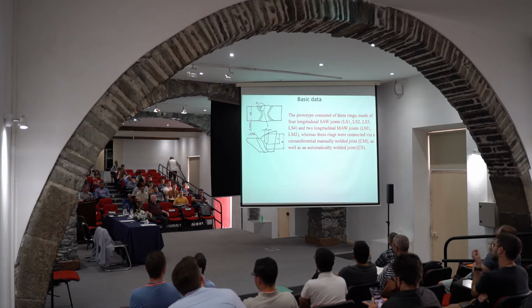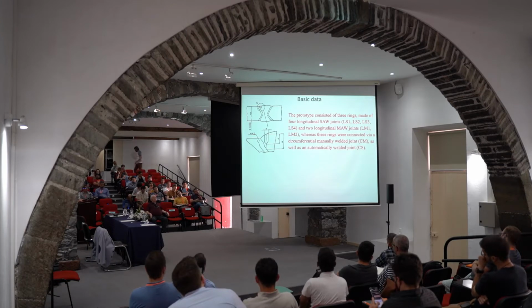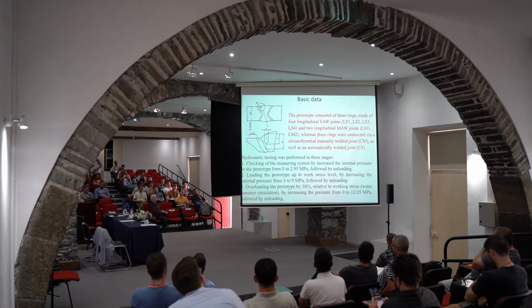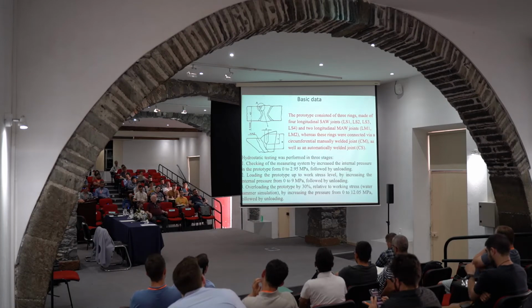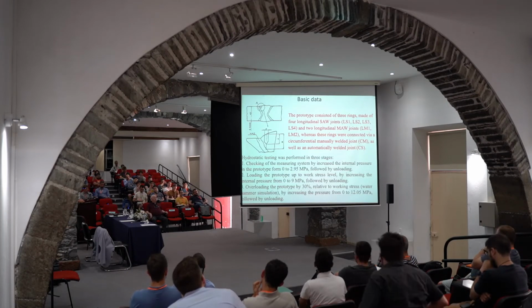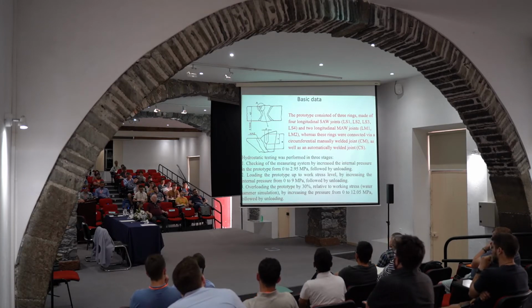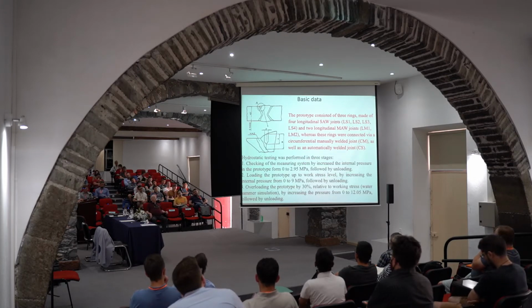So you can see some basic data explained and written, as I already told you. And this is important, how testing was done. It was hydrostatic testing, which was done in 3 phases. First was just to check the measuring system. Then the second one was to load the prototype up to work stress level. That was up to 9 megapascals, 90 bars. And then to overload the prototype by 30%. And that third step produced some surprising results, but still we could prove fitness for purpose. Some results are shown here, but once again.